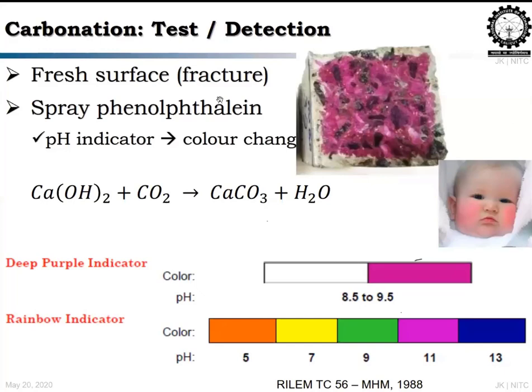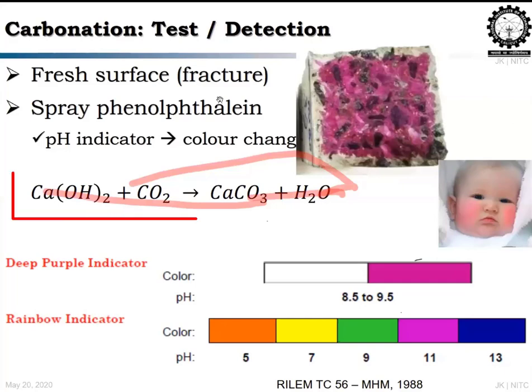We have a lot of carbon dioxide because of industrialization, heavy traffic, and many other parameters. So what this carbon dioxide does is get into the pores of the concrete, and if moisture is present, it reacts with calcium hydroxide or CSH, which is there as the strength-giving structure, and forms carbonic acid and reduces the pH, and also forms calcium carbonate.